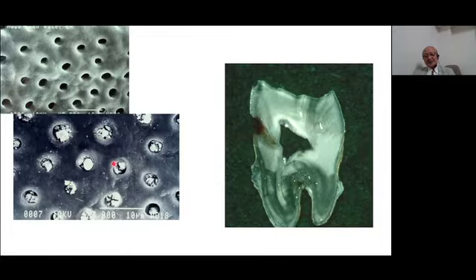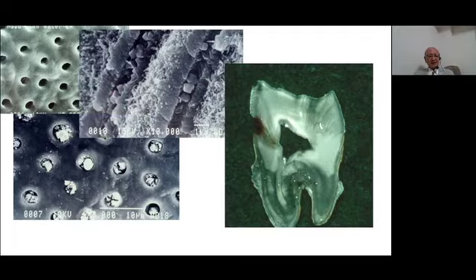On the other hand, this is the dentin surface after the phosphoric acid etching, but this is the caries affected dentin. Even after the phosphoric acid etching, the mineral deposition in the tubules still remained, occluding the tubules. So that's why we can obtain very good bonding, and the patient does not have postoperative sensitivity. Then, when I cut this specimen, you can see this kind of mineral crystal deposition in the dentinal tubules. It's a very excellent performance of the natural tooth.